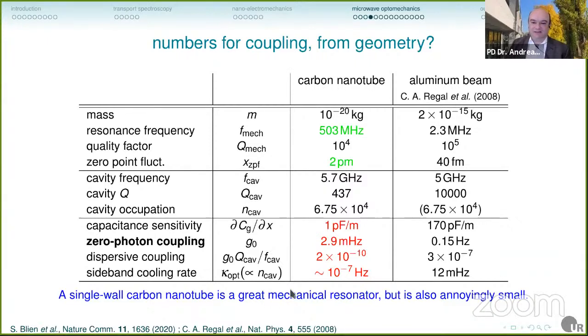The microwave resonator, the length is given essentially via the resonance frequency and the wavelength. And there we end up with a scale of 1 centimeter. If we want to have a nanotube that traps single electrons in well-defined quantum states, we are in the length scale of 1 micron. And if we look at the vibration, then the typical deflection is on the order of 1 picometer. And you can imagine that a deflection of 1 picometer is not influencing a 1 centimeter large system that much. So that's basically the reason for the red numbers here.